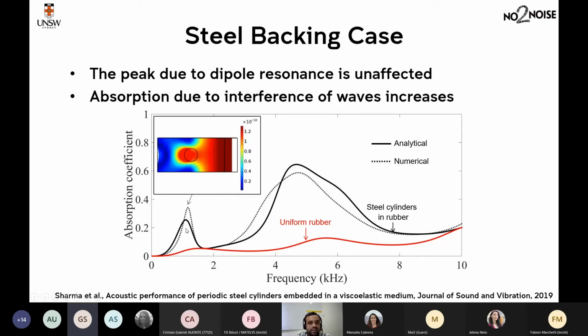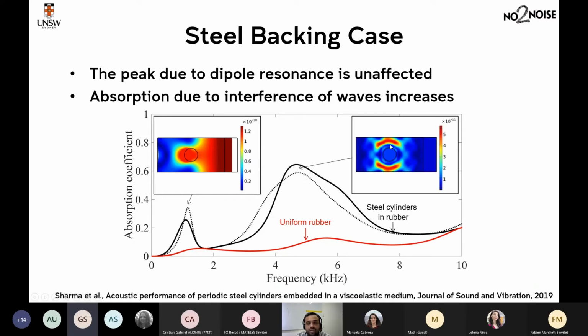So again, here, the first peak, which is due to dipole resonance of inclusions, does not depend on the type of backing. The sound absorption is more or less the same, whether you have hard backing or water backing. But here, the second peak, which is due to interference of waves scattered by the inclusions and those reflected by the backing, you see that this peak increases significantly when you have a rigid backing.